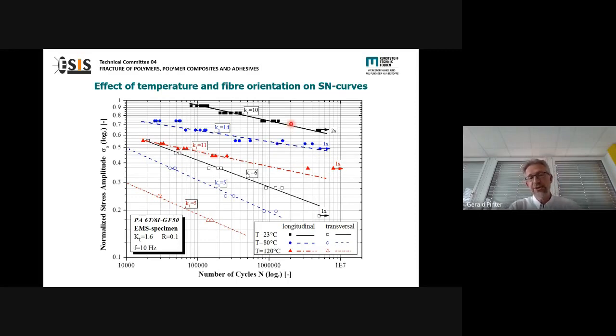And what in addition you see in this diagram is the failure curve for a longitudinal fiber distribution. That means in the direction of the injection molding machine. So here you are testing the specimen in fiber orientation. That means, of course, you have much higher failure cycles than if you test transversal to the injection direction, because in this case you typically also have 90-degree oriented fibers, and the failure cycles will be much lower. So you need all this information from these Wöhler lines to go into the calculation procedures.